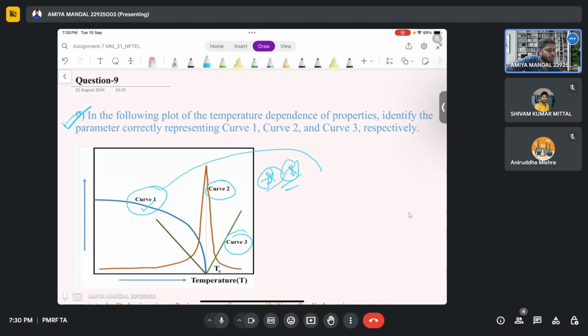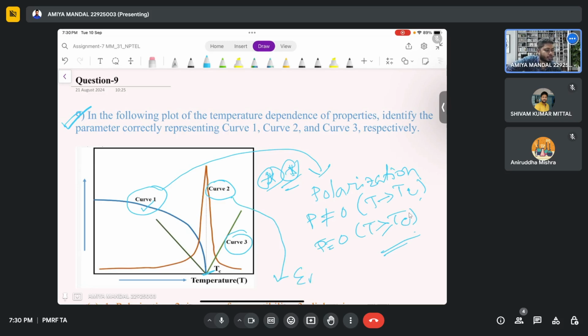So curve one is nothing but the polarization curve. This is the Curie temperature polarization curve, in which polarization decreases, and the P value is not equal to 0 up to T equal to Tc. The P value is 0 at T greater than or equal to Tc. And curve 2 is the dielectric constant curve, epsilon r. There is a peak at Tc. The maximum value of the dielectric curve is observed at Tc.